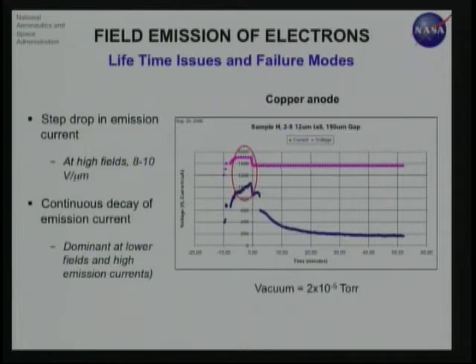When you apply such a force, you're slowly pulling the nanotube up, but the nanotube is not completely removed from the surface because it is held down by the surrounding nanotubes. So you're constantly increasing the nanotube's distance, and it keeps moving up. As a result, the gap keeps decreasing. When the gap keeps decreasing for the same applied voltage, your field starts to increase because it is V by D. And as a result, the current starts to go up to a point where it leaves the rest of the nanotubes or the cathode surface, and then just goes and attaches itself to the anode, and at which time a catastrophic failure happens. That's the reason why you see a step drop in current here.